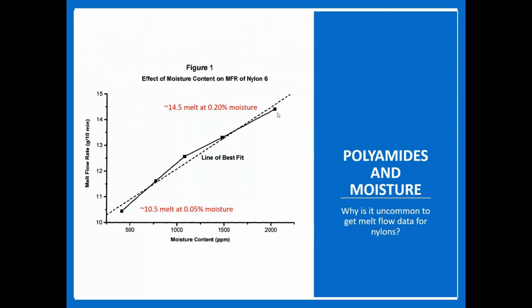But they're going to vary. And so getting a melt flow test on that would vary. It's why we don't provide melt flow testing for nylon. What you can get though is relative viscosity or viscosity number testing, because then it takes all of the moisture out as a variable. So keep that in mind if you're being asked or you get ready to maybe ask us about melt flow testing. It's highly unlikely that we're going to have it or get it, specifically because nylons are so affected by moisture.